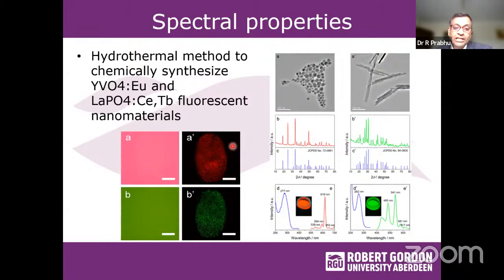And with these dyes, with exciting using 250 nanometers illumination, you can see it is giving very large contrast. Again, for the second dye or second nanoparticle powder, you can see green emission giving a very sharp or contrasting picture. And they used this type of nanomaterials, and you can see the absorption band for the red one. This is Eu-doped nanomaterial, which has strong absorption around 277, while for the green one, strong absorption around 262 nanometers. So exciting at this wavelength can get emission around 619 for Eu and these green emissions for the Tb cerium doped material. And these are the typical pictures of the nanomaterial.